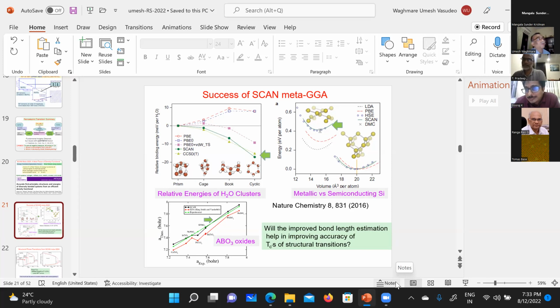Yeah, Suraj, it's good to hear what you found. What it suggests is, if you want, you can first do the initial relaxation and structure determination using GGA plus D3, and then later switch to SCAN meta-GGA, where the final refined calculations, which are selective ones in a few of them, can be done, where you have access to more accurate electron density and energetics.